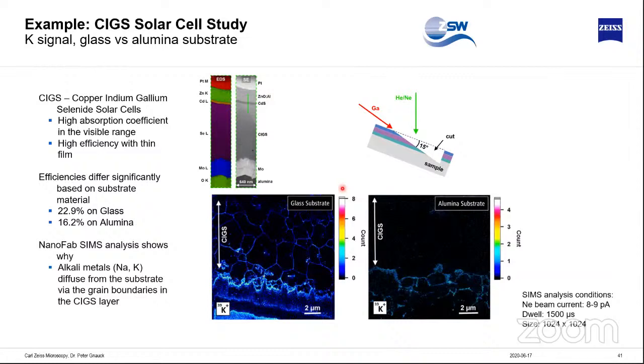Another example would be solar cells, copper indium gallium selenide solar cells. It's typically a stack here of different materials. We can look at that in EDS, also with the SEM. What is interesting about these solar cells is there's a difference in efficiency if they're based on a glass substrate or on an alumina substrate. Glass substrates seem to have a higher efficiency than an alumina substrate. And if we want to investigate why, then we can also do an investigation of this structure here with SIMS. And what we see immediately, if we take a solar cell built on a glass substrate, is that the potassium of the glass migrates into the grain boundary of the solar cell, and that probably gives a much better efficiency compared to if we have an alumina substrate.